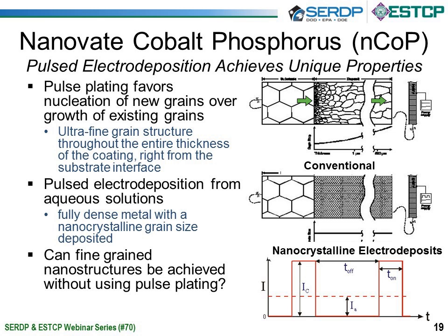And the ultimate end result of the coating is a fully dense metal with a nanocrystalline grain size. And I should mention at this point that there's no powders involved with the production process. We go from ions in solution to fully dense metal on the plate, and there's no intermediate powders involved. So one of the objectives of our current project, in fact, was looking at whether or not we can produce these structures without the use of pulse plating. I'll go into that a little bit later when I talk about the project.